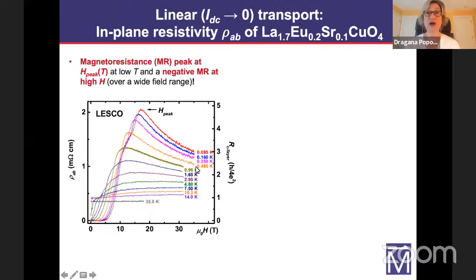This was actually quite surprising, because a peak in the magnetoresistance of cuprates had not been observed before, even after all these decades of work. We also see that the position of the peak shifts with temperature, and it seems that it represents some kind of characteristic energy scale. So we decided to track that.